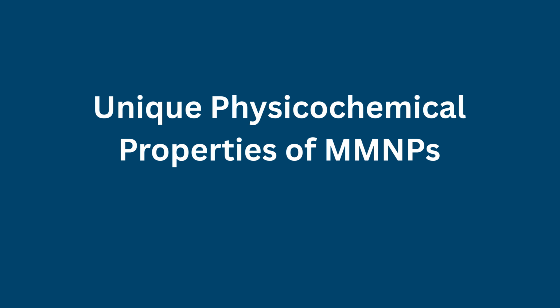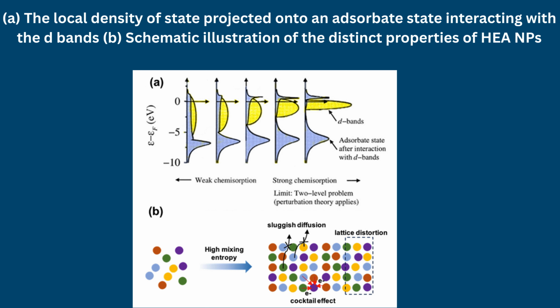Unique physicochemical properties. The remarkable properties of MMNPs arise from synergistic interactions among constituent elements. Electronic interactions between surface and subsurface atoms alter the d-band center of active catalytic sites, thereby modifying the adsorption energies of reaction intermediates. Lattice mismatch between different metals introduces compressive or tensile strain, which further tunes catalytic activity. The local arrangement of atoms on MMNP surfaces generates distinct adsorption geometries and reaction pathways. These ensemble effects can significantly improve selectivity for complex multi-step reactions.